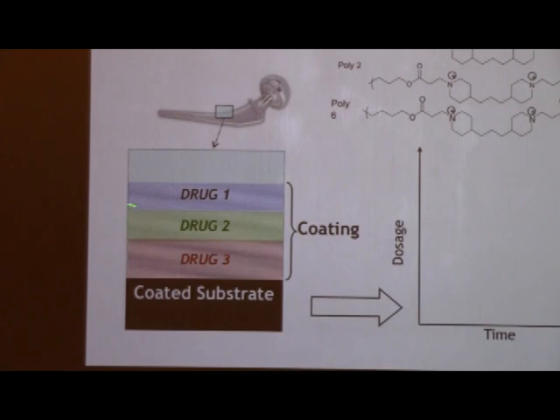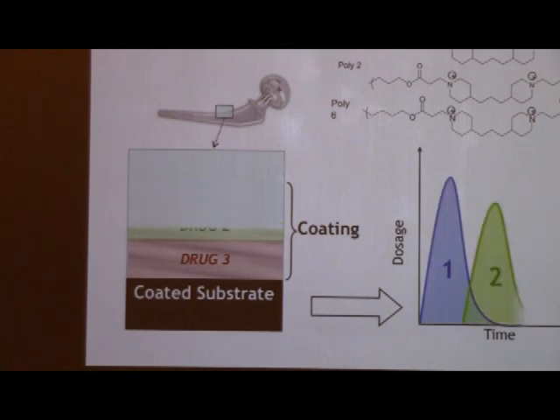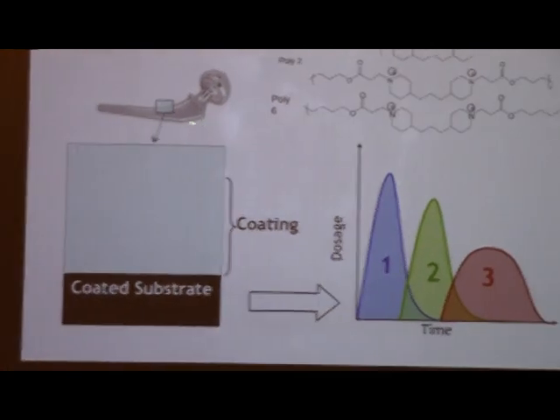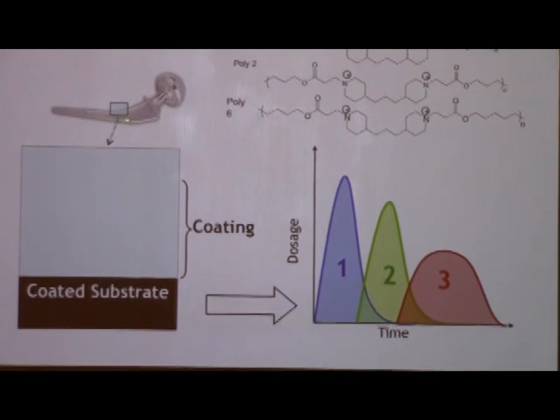On top of that, if I'm able to successfully create some degree of separation between the drugs when they're layered into these films, then I might be able to have a surface-based erosion, and that would allow me not only to have them release at different rates or speeds, but also to have them release with a staggering in the time frame that they get introduced into the body. So the general idea here is that you might be able to have an intelligent thin-film coating that can release drugs at different times. Now, where would we want something this sophisticated?